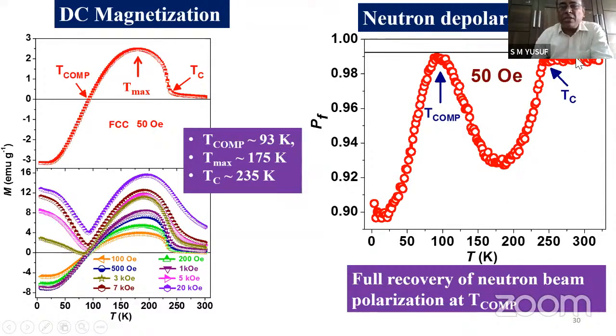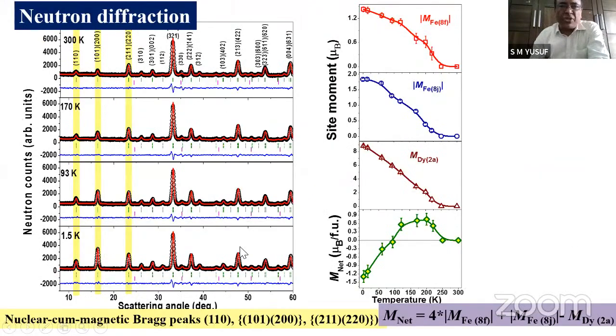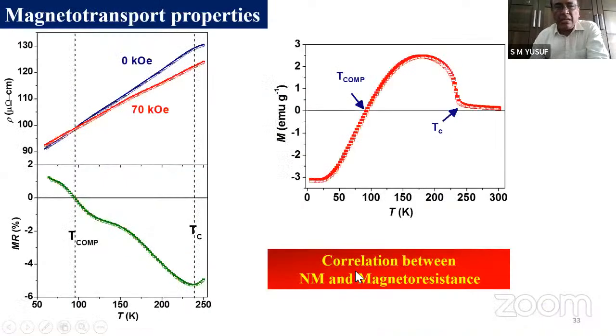And this is a neutron depolarization study. Again, it corresponds to the reversal of magnetization. This is the compensation temperature, full recovery, and so on. And by doing neutron diffraction, we could again measure the site moments and the net moment, which shows magnetization reversal. But here is the magnetoresistance data. See the resistivity as a function of temperature at two fields, 0 kilo-oersted and 70 kilo-oersted. We see the crossover, and when you plot the magnetoresistance of this material, then you see magnetoresistance also passes through the zero.